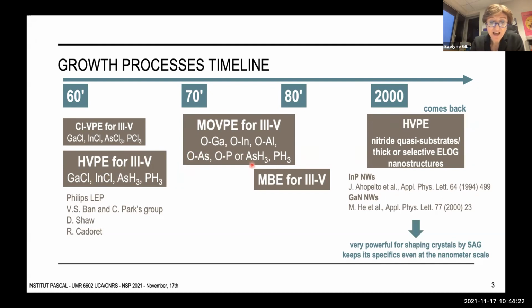Nevertheless, a few groups have continued to develop HVPE, and HVPE came back some 20 years ago when we were looking for quasi-substrates for the revival of the nitride compounds. Quite surprisingly, HVPE revealed itself to be competitive when it comes to shaping structures or crystals by selective area growth or vapor liquid solid VLS growth, including the nanometer scale, with these pioneer papers about the growth of gallium nitride or indium phosphide nanowires.